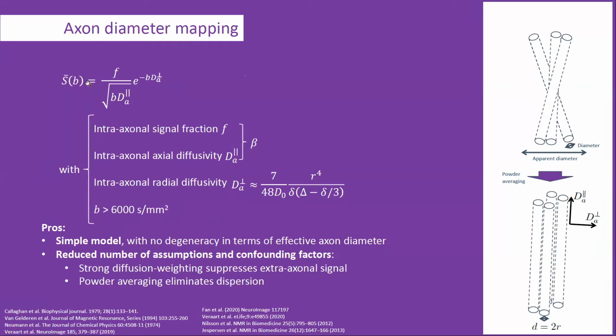If we have to model the powder average signal inside of the axon, we actually only need 3 parameters. And this model is actually very old. It was established by Callaghan in the 70s. It basically says that our powder average signal decays as 1 over the square root of the B value, multiplied by a correction term that depends on the radial diffusivity inside of the cylinder, the axon, and therefore depends on the radius.